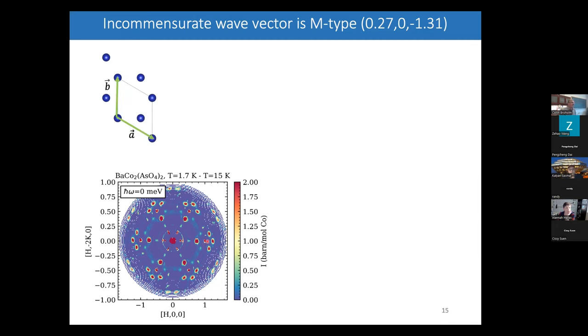And just to get ourselves oriented, this is the real space honeycomb lattice with the A and B vectors associated with that. The reciprocal lattice vectors are going to be perpendicular to real space vectors. So A star is perpendicular to B, B star is perpendicular to A. And this is the orientation of the A star and B star direction of my reciprocal space. Where I see the satellite reflection is in these locations here, which is like an H00 type location. That is the point that we call the M point, or in other words, the satellite peaks lie along the gamma to M direction of reciprocal space. And that turns out to not be possible to obtain by the Kitaev model alone, to obtain an instability at the M point.